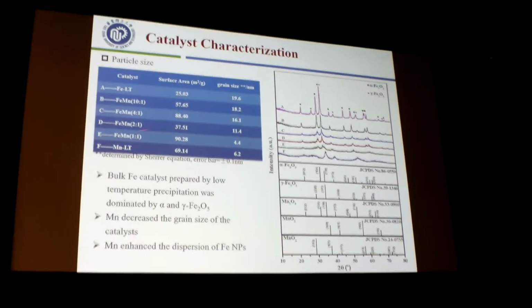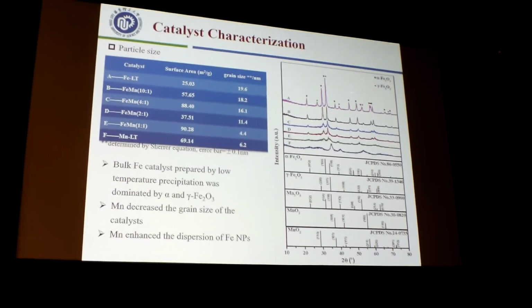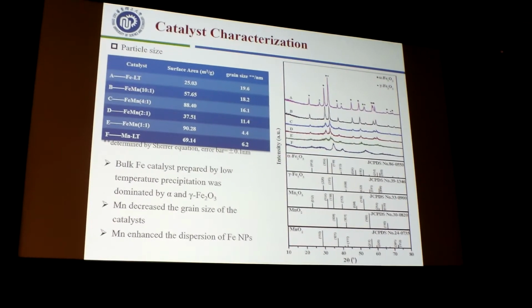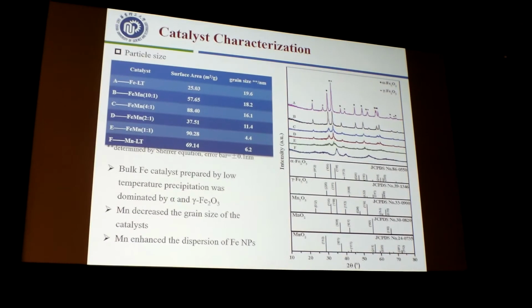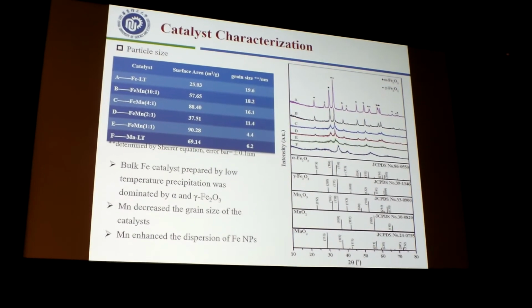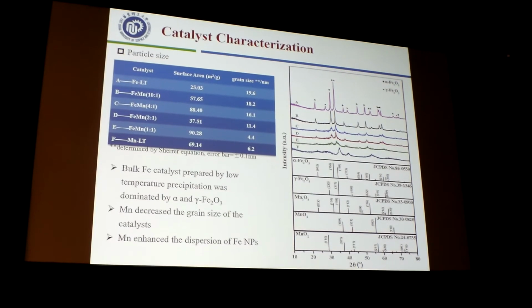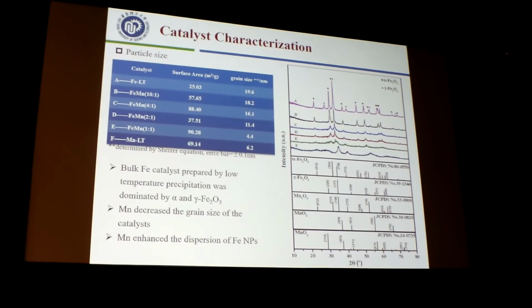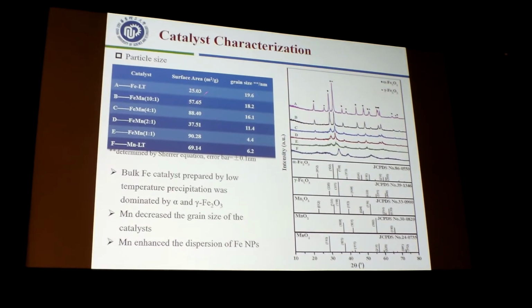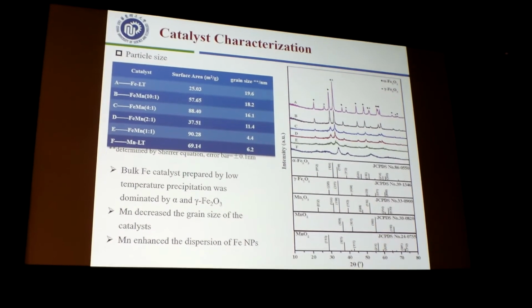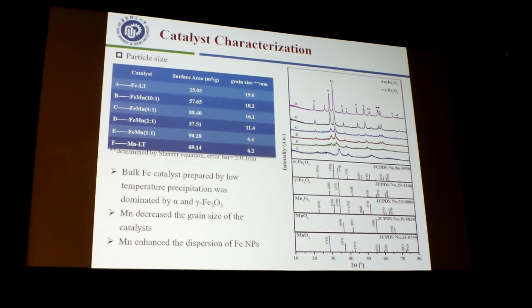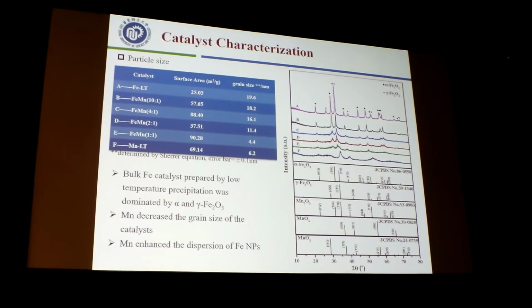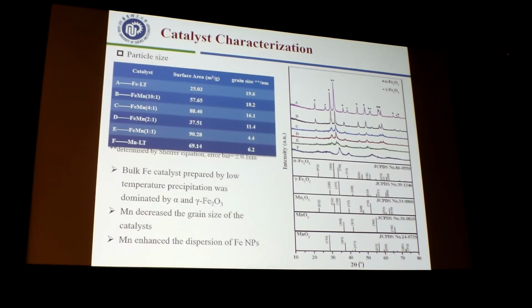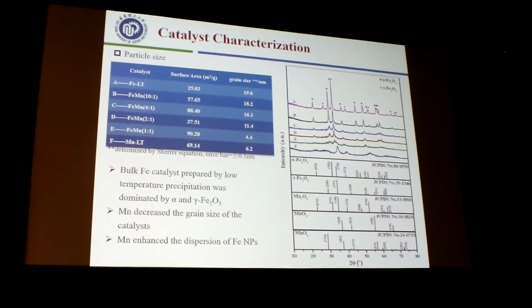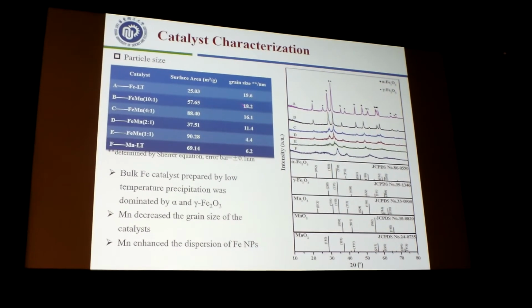And to elucidate the effect of manganese for the FTS reaction, we employed different characterization techniques during catalyst activation, catalyst reaction, and on the spent catalyst. For the calcined catalyst, we first analyzed the textural structure using BET surface area and XRD. It can be seen that as we increase the loading amount of manganese, the particle size decreases.